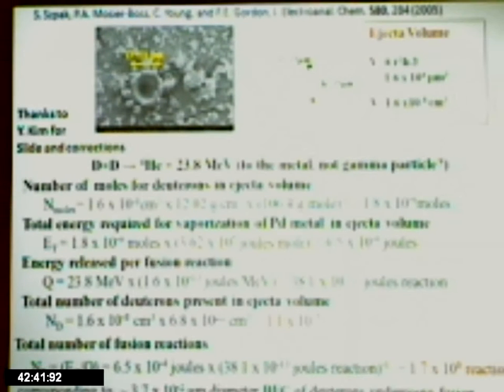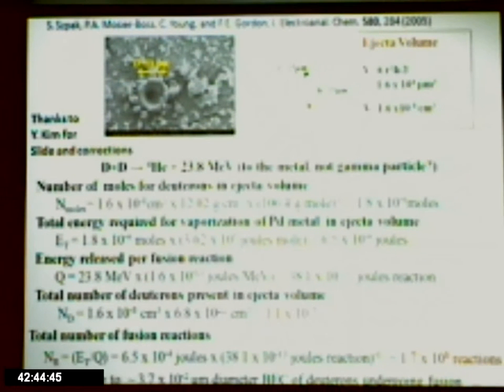Now, this group that's cited here, let's see, Young Kim, for corrections to this basic method, reapplied this method to the question of the crater formation. The question was, okay, how many D plus D fusion reactions would have to occur to create the heat release, again under the electrolyte, necessary to see this crater formation in the case of the work that was done at Energetic Technologies. It turns out to be about 200 million reactions to create enough heat, fusion reactions, to have this effect on the surface, if in fact that's the origin of these craters.